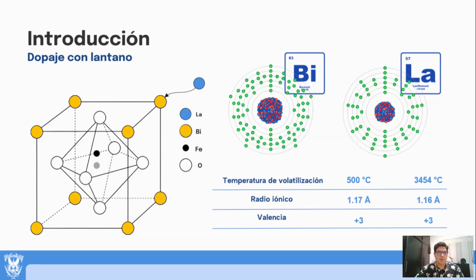To overcome these limitations, an effective strategy has been rare earth doping, particularly with lanthanum, which substitutes bismuth sites in the crystal structure. The similar ionic radii between lanthanum and bismuth enables efficient substitution without introducing significant lattice strain. Lanthanum doping has multiple beneficial effects.